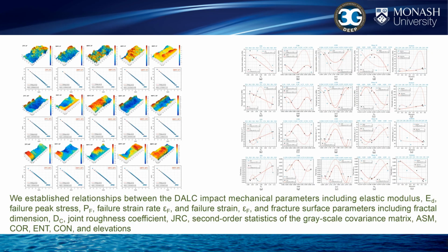We established relationships between the DALC impact mechanical parameters, including elastic modulus, failure peak stress, failure strain rate, failure strain, and fracture surface parameters, including fractal dimension, joint roughness coefficient, second-order statistics of the grayscale covariance matrix, and textural parameters including ASM, COR, ENT, CON, and the elevation parameter.